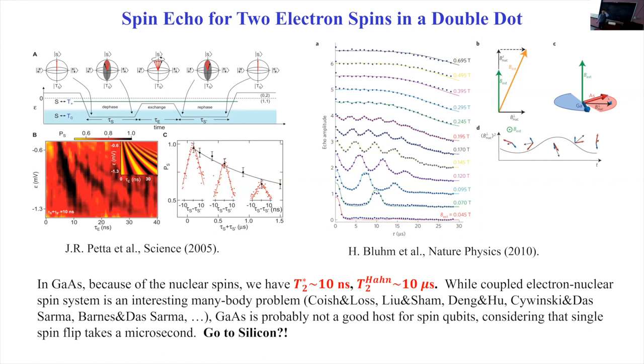spins through that interaction. Even at the dilution fridge temperature, 100 millikelvin, and the electron temperature, well, 20, 30 millikelvin base temperature, for the nuclear spins, in a relatively small magnetic field, let's say 1 Tesla or 0.5 Tesla, nuclear spins are still thermal. The nuclear magneton is so small that the nuclear spin distribution is basically a thermal distribution. So it points every which way.